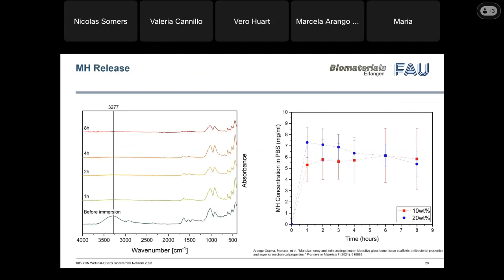So of course, one of the ideas when we have these natural compounds is to know the release of the phytotherapeutic. In this case, we were studying the release of Manuka honey, both with UV-Vis and also with FTIR. And we didn't see good results here, because the honey was released very fast. You can see that after 1 hour, all the honey was basically released.